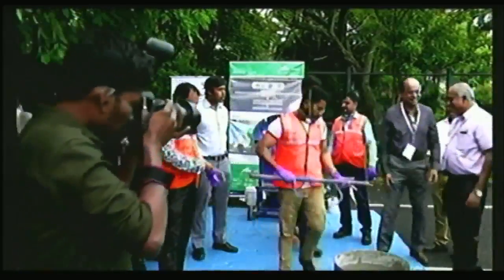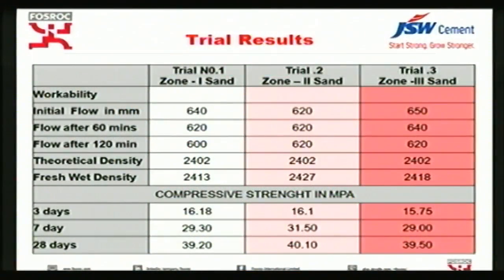Thank you and congratulations. Just to inform you about the V funnel, in fact, we did the V funnel for this. Since we are using 35% 20 mm aggregate, it was around 22 to 25 seconds. We measured that V funnel before coming here. But when we use the 10 mm downsize aggregate, it is very close to 13 or 14 seconds.